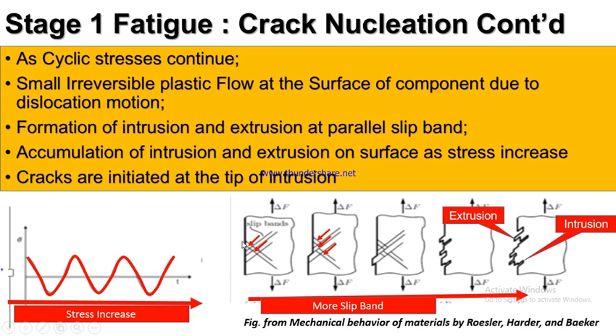You can see the surface was uniform. At this point where the slip bands have increased, you can see that there is a discontinuity at the surface of the material. Once this continues, we begin to see more slip bands, and you can see a protrusion coming from the surface of the material. By so doing, we begin to have what we call surface intrusion and surface extrusion. So these are the intrusion and extrusion in the system.